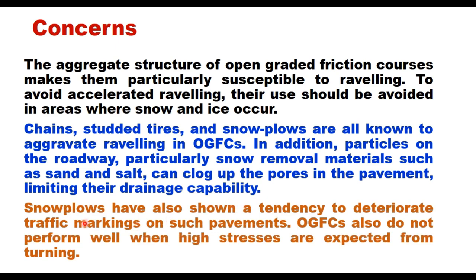Snow plows have also shown a tendency to deteriorate traffic markings on such pavements. OGFC does not perform well when high stresses are expected from turning. OGFC is more expensive per tonne than dense-graded HMA, but the lower density of this mix somewhat offsets the higher cost. Dust, de-icing sand, or even low-speed traffic can degrade the performance of OGFC in the field.